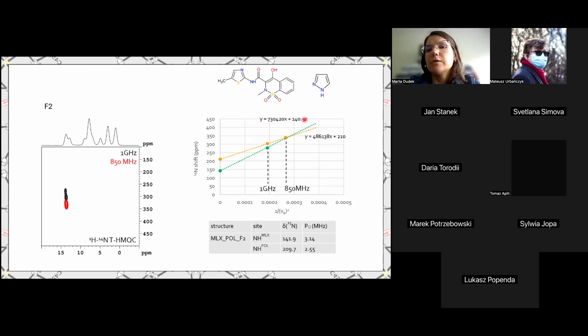So what we can see here are the equations that we got from those experimental points. What is important here is that the B values that we got from this equation are in very close agreement with the nitrogen-15 isotropic chemical shift, because we assume that nitrogen-14 and nitrogen-15 isotropic chemical shifts should be the same, more or less, so to say. So you can see that both values for both NH sites are in agreement with what we saw from this plotting, and we were able to determine PQ values. They were also in very good agreement with the calculated ones.